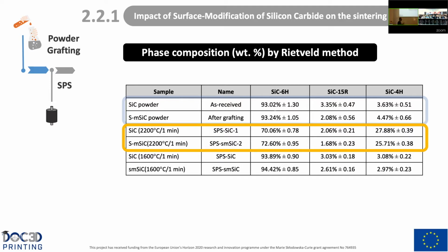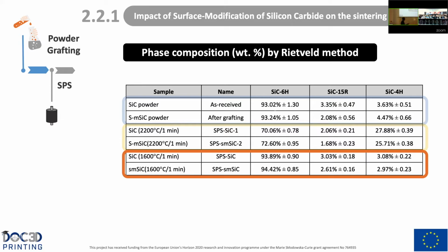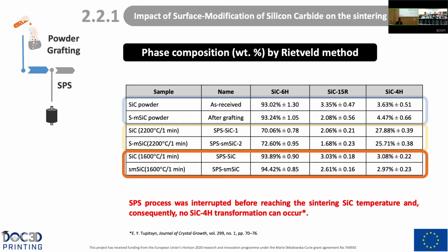are observing some transformation from 6H to 4H. But actually we are not able to observe this phenomenon in the powder that we stop at 1,600 degrees. Actually, here we cannot observe this transformation from 6H to 4H. Why? Because actually the spark plasma sintering process was interrupted before reaching the sintering silicon carbide temperature, and consequently no silicon carbide 4H transformation can occur, as it is reported in detail.